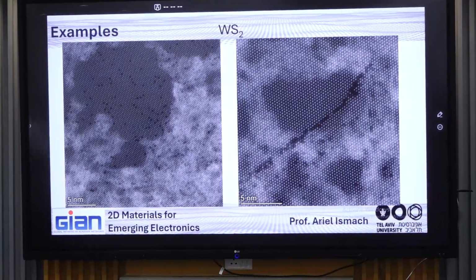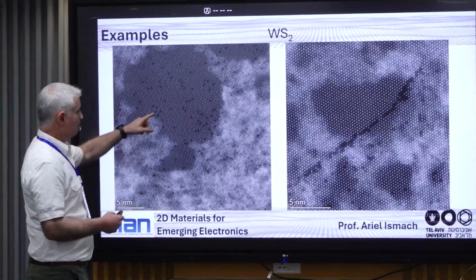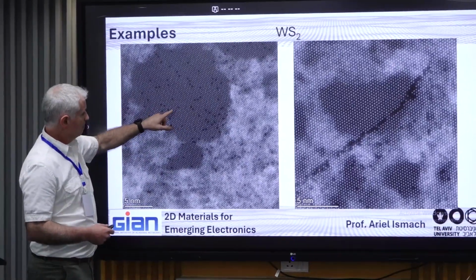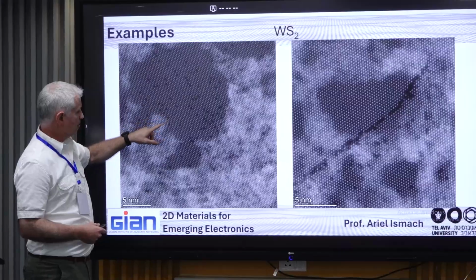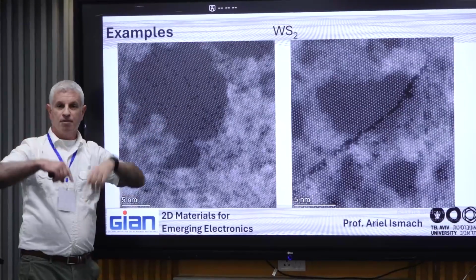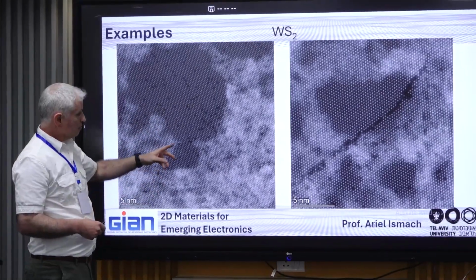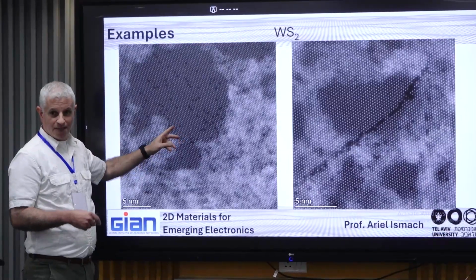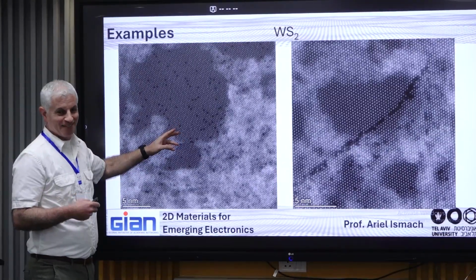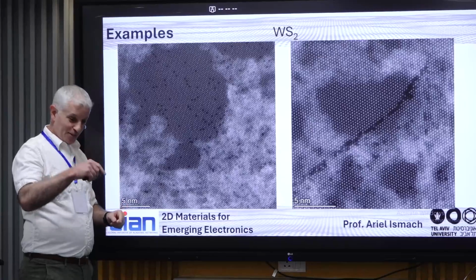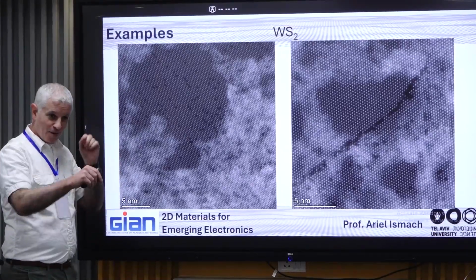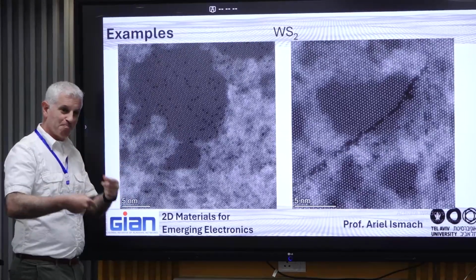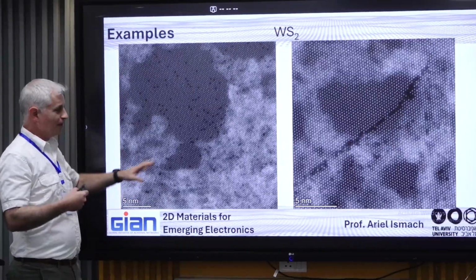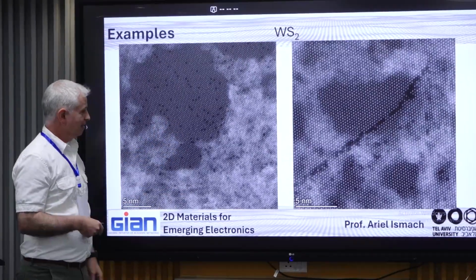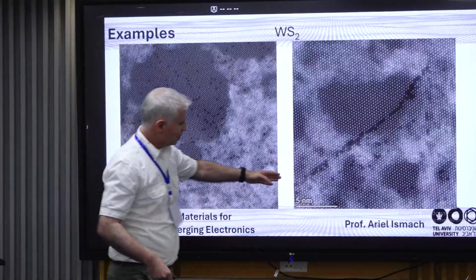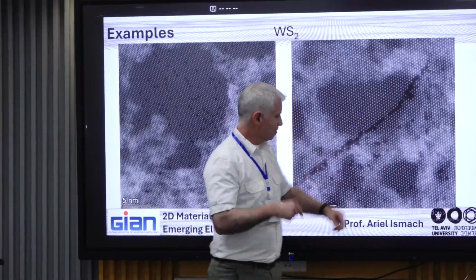and these point defects, I couldn't find the movie. These point defects that you see here, basically most of them are sulfur deficiencies. These were not here. My samples are not so defective. But while imaging, you see that. You see how the holes are created as time passes. So you need to be very careful in studying. Here you can see even the line defect.